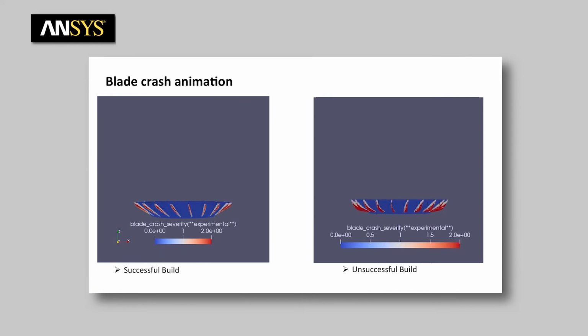And so we have something that we call a blade crash severity. So if something bends up in Z, it can hit the blade, and depending on the design of your blade that's pushing the powder, it may crash or not. So gray means there's a chance of it scraping. Red means it might hit kind of hard. And at this geometry, the little tips of this were showing some scraping. And indeed, they said, yeah, it scraped, but not enough of the material was scraping to actually fail the build.